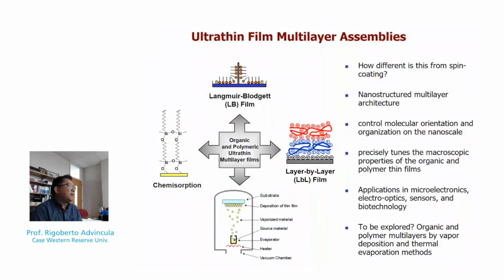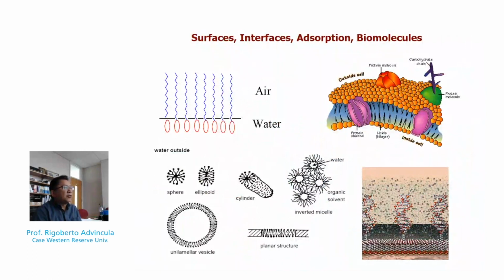So let's first talk about ultra-thin film multi-layers and assemblies. I like to use this view graph to introduce that nanostructured films, from polymer to inorganic to hybrid material, have many advantages in terms of nanostructuring when it comes to very, very thin films. I'm talking about film thicknesses from 1 nanometer to hundreds of nanometers, and they can be ordered using chemical adsorption methods or by physical adsorption methods, where one can use Langmuir-Blodgett films, layer by layer deposition, surface initiated polymerization, or vapor deposition.